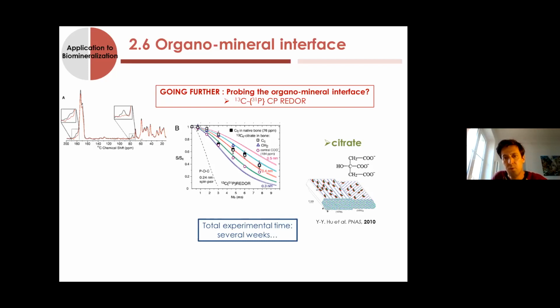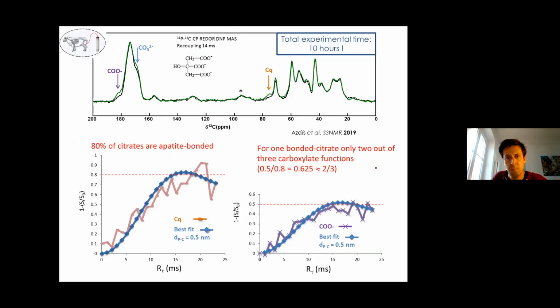So we decided to do the same, but by first using DNP, dynamic nuclear polarization, to boost the NMR signal. And instead of one month, we were able to make this kind of experiment in just 10 hours.